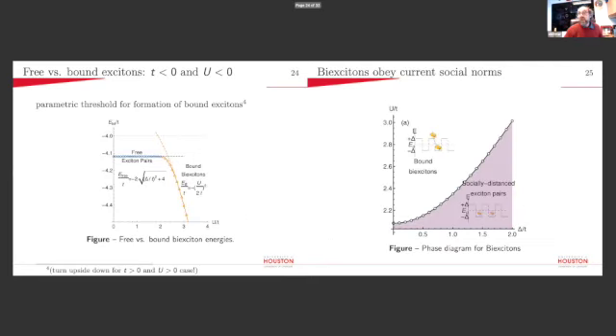the crenellation. So what you can do then is take this and analytically come up with a parametric threshold for the formation of bound excitons. Just simply say that the model is going to tell me what the threshold for free exciton pairs must be. Let's take U equals 0 because they're not in contact with each other anymore. That's an asymptotic limit, and you wind up with this sort of plateau. Delta is the crenellation, T is the hopping integral, and this is the constant. So if you're below or above 4, depending upon if you're a positively or negatively attracted system, there you are. You get bound states as soon as you cross this threshold.